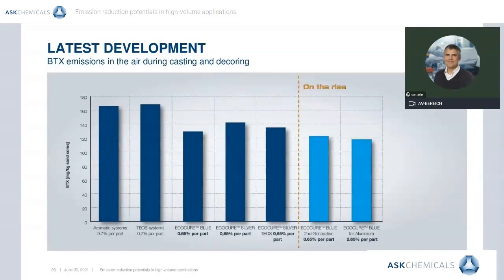And all these systems also benefit from the performance of the EcoCure Blue technology, and in many cases, the binder content can be lower, which as explained before, is the best way to further reduce emissions. So the EcoCure Blue second generation will be even more reactive and efficient, allowing for further binder reduction and therefore a further reduction of emission and a further improvement of the total cost of ownership. The new aluminum solution will not only be VOC-free, but will also reduce gas pressure and be characterized by low thermal distortions. Okay, it was a brief overview of the promising solutions that will come to market this year and which we will present to you in a much more comprehensive way in a few weeks or months.